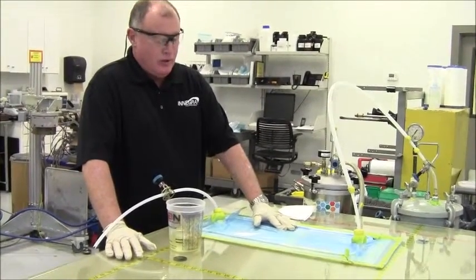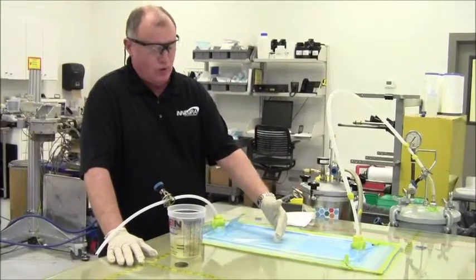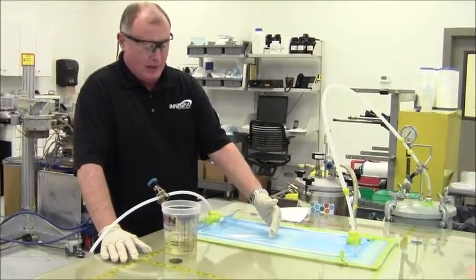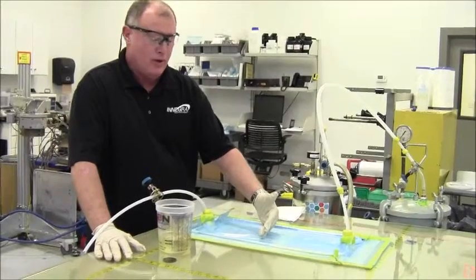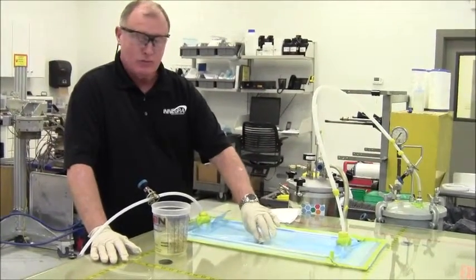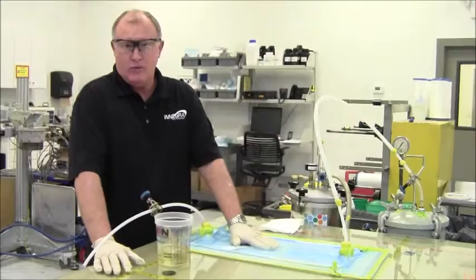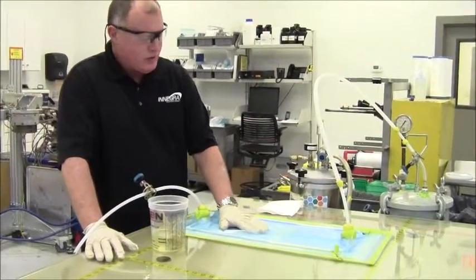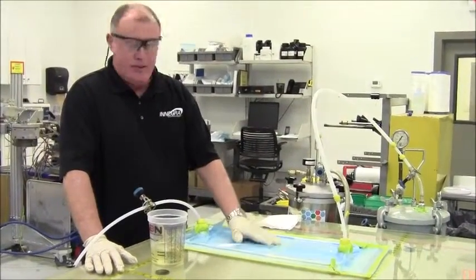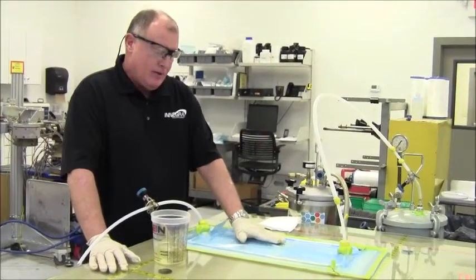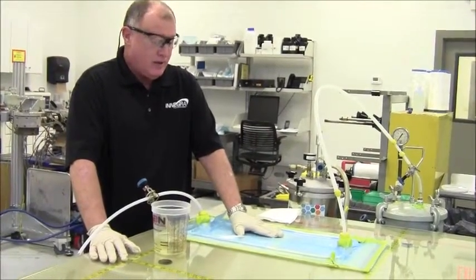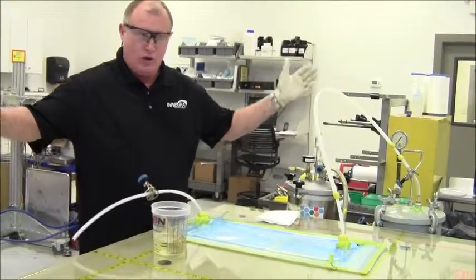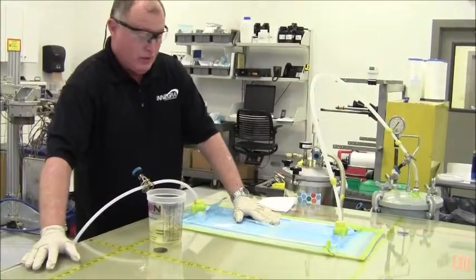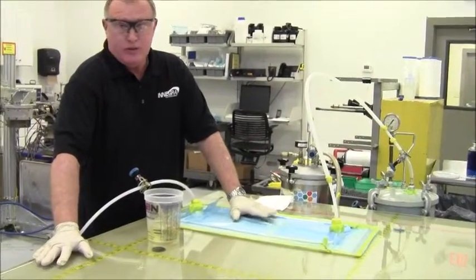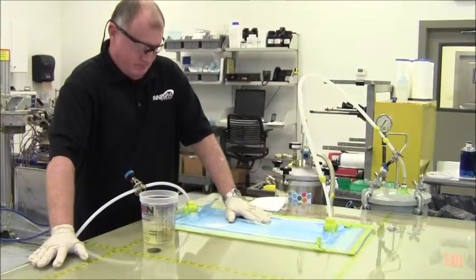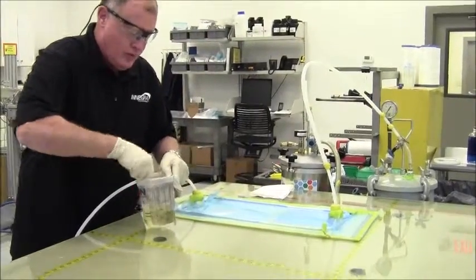I like to, when I do my infusions, stop my flow short and allow the balance of the material to migrate through the part, keeping the bag as tight as possible to keep my resin content as low as possible. In this particular part, we've got a medium green flow media. That medium green flow media is going to take approximately 600 grams per square meter. So that's been put into our calculation today. So without any further ado, let's go ahead and get this infusion rolling.